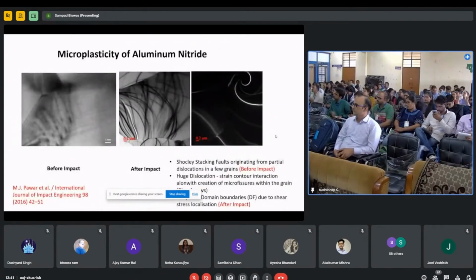So then we looked at the microstructure of the impacted ceramics. What we found is that ceramics, as I told you, is very brittle in nature, and that is due to the high Peierls stress. And this brittleness is only because ceramics contain dissimilar ions, while metals consist of similar atoms. In a ceramic crystal structure, you get dissimilar ions. When these ions move to form a dislocation, what happens? A positive ion comes close to another positive ion, and it repels. Similarly, negative ions have an attraction with positive ions. So naturally, the bonding between the ions is very strong. As a result, the Peierls-Nabarro stress, which creates the shear of the crystal structure, is very, very high. So ceramics are not at all ductile, they are brittle materials.